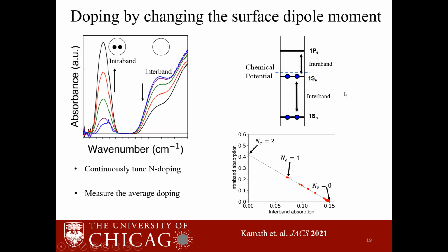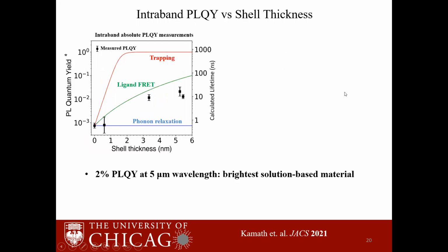So now that we have the synthesis of the thick shell and we have a way to dope the quantum dots, we have measured the quantum yield of the quantum dots as a function of shell thickness. So here, this is a graph where the quantum yields are measured in an integrating sphere. So these are absolute quantum yield measurements. And this asterisk is to mention that these quantum yields were measured at low values of doping, because this is the value at which the quantum dots are the brightest.